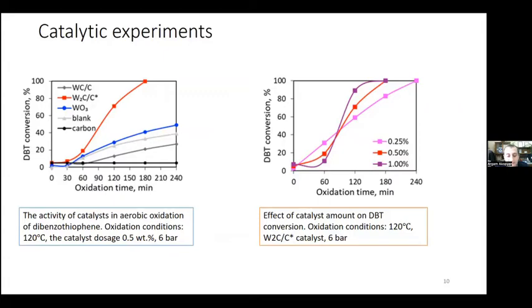The results of the experiment involving carbon shows that the metal center tungsten plays a key role in the oxidation of sulfur compounds. This, once again, emphasizes the importance of tungsten in an intermediate oxidation state for the activation of oxygen.